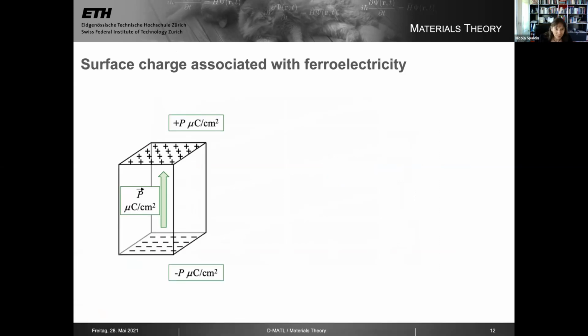So that leads us immediately to see that associated with ferroelectricity, associated with the ferroelectric polarization, is a surface charge. Just by looking at the units, we can see that immediately. And this is really the case. Here's a kind of bulk solid. Again, it could be a thin film. It could continue in the direction in the plane. And the bulk polarization, the electric dipole per unit volume, is some value, let's say P, perpendicular to the surface, microcoulombs per square centimeter. When I make a top surface, then above this spontaneous polarization, I have then a surface charge of plus P microcoulombs per square centimeter. So the size of the surface charge is equal to the size of the bulk polarization.